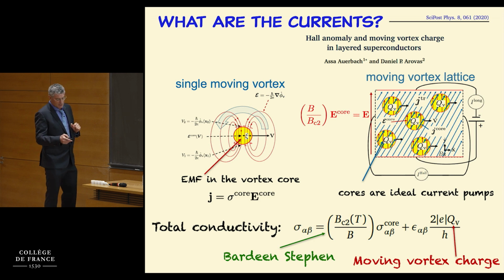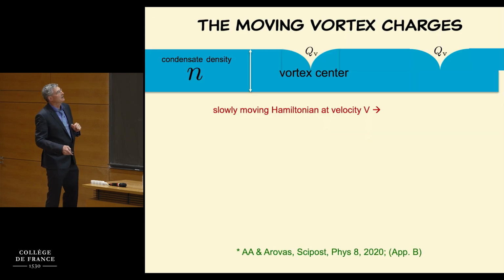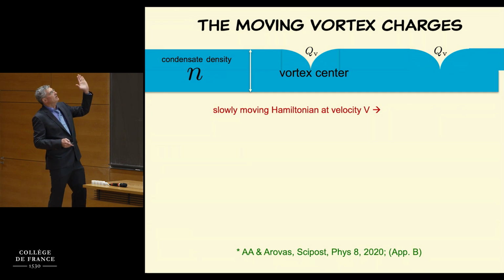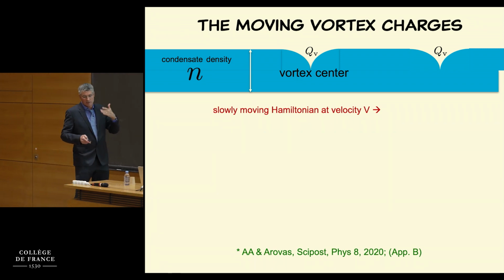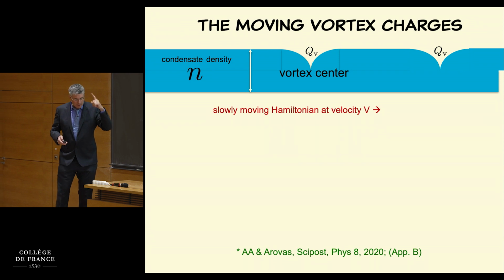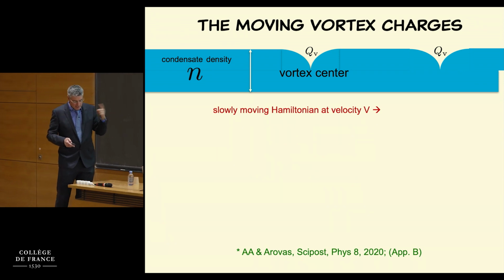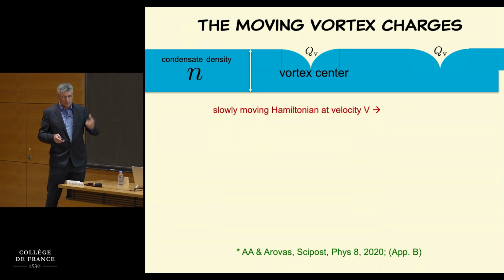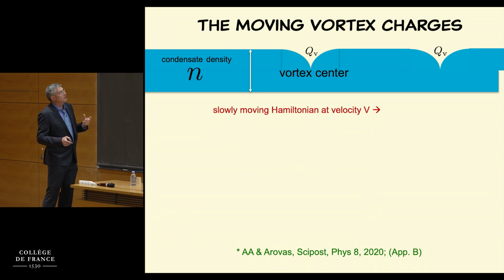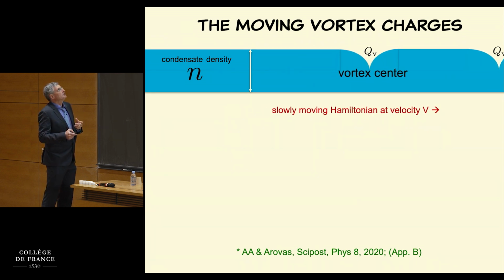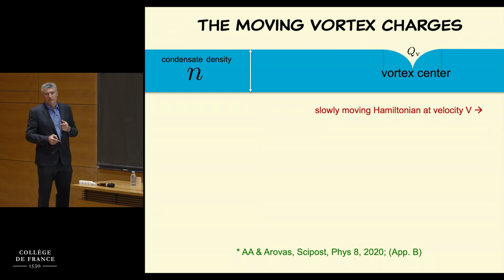And the question is, what is this Q? And there's been arguments about vortex charge, so I want to show what we're saying here. This is actually nice in terms of theory of transport. So imagine you have a condensate of moving vortices. And in every vortex center, there's a depletion of charge, let's say. That's the usual case, because the kinetic energy of the rotating currents around the vortex would actually push out charge to reduce the energy. And if you have that condition, you get a charge depletion Q_V. And notice that you have a motion. And the question is, what is the current associated with this motion? So one would say, oh, it's just the condensate density times the velocity. The question is, is that right?